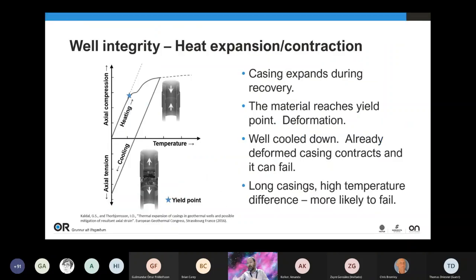So the problem is that the casing expands during the recovery, and the material reaches the yield point, and everything deforms. And what happens when the well has to be cooled down? The already deformed casing contracts and it can fail. And this is even a bigger problem with long casings, and when you have higher temperature differences, so it will be more likely to fail. However, there is a recently available solution to this, the so-called flexible coupling.